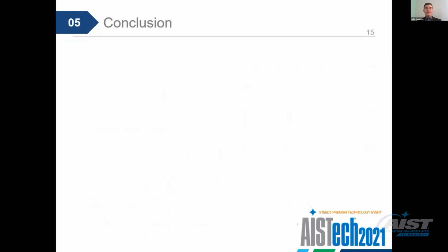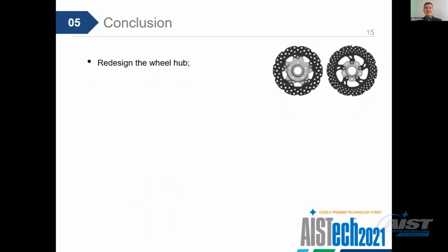So, as conclusion, after the results, the team designed a new wheel hub with the same material, the same aluminum alloy 7075, but with a new geometry, as you can see. And this geometry allows the part to be further away from the friction area of the brake discs, facilitating the heat dissipation and helping to avoid the conduction between the wheel hub and the brake discs.